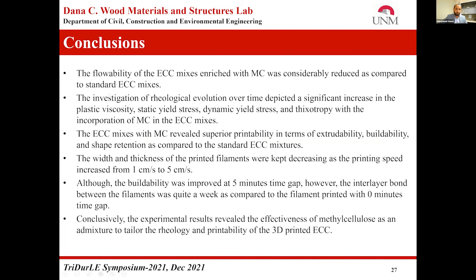In the end, we can conclude that the flowability of the ECC mix was significantly reduced because of the water retention capacity of the methyl cellulose, and the rheology was improved over time. If we see the rheological parameters such as plastic viscosity, yield stress, and thixotropy of the methyl cellulose enriched ECC mixes, the printing trial shows the extrudability and buildability and also the shape retention. If we compare to the standard ECC mix, the mixes with addition of methyl cellulose have very superior printing quality.